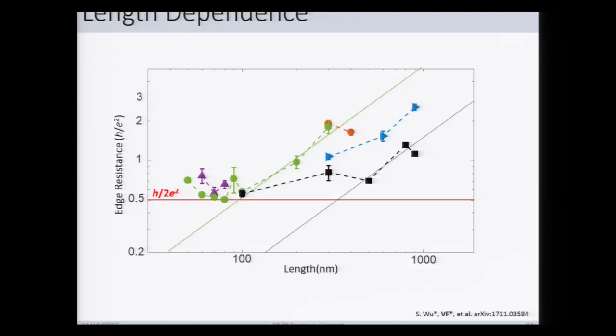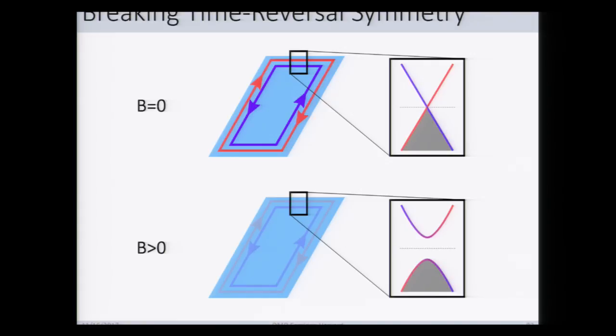Okay, so this is all well and good, and now the next thing is to see what happens when you break the symmetry that protects the topological state. If we go back to this cartoon image of these counterpropagating modes at zero magnetic field, we can zoom in and imagine a band structure for these modes. And if you have a clean edge, you can say that you have a Kramers point here. So you have this mode with one group velocity and a particular spin in purple, and the other one in red. And at this point, these two states are degenerate. In particular, you have a spin degeneracy there. And when you have a spin degeneracy, a magnetic field can break that via the Zeeman effect. And in doing so, you can generate a band gap in the edge mode. So here, schematically, these edge modes have become less conducting. And in particular, if your chemical potential is inside the gap, it should behave like a simple insulator. You've broken the topological protection of the system.